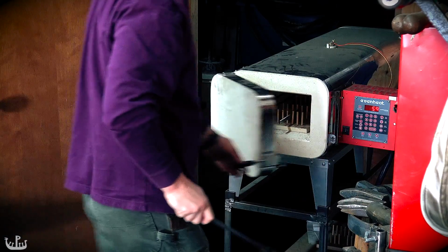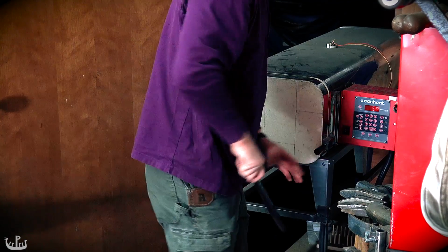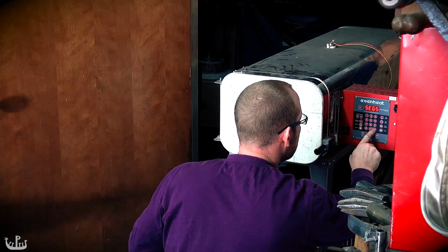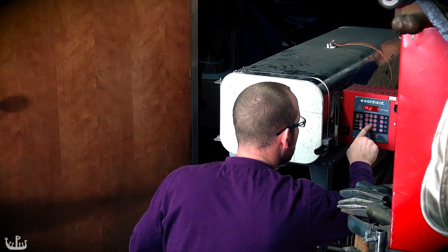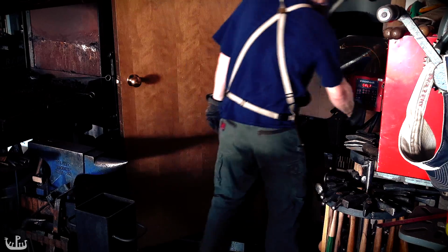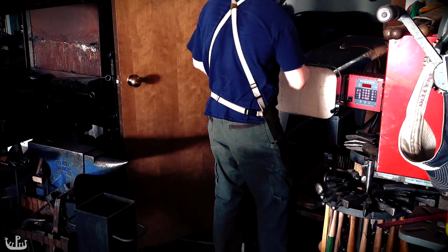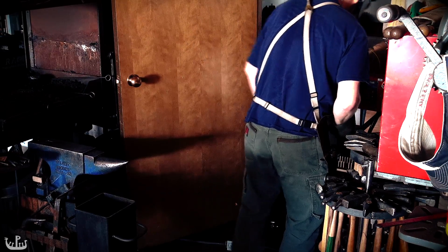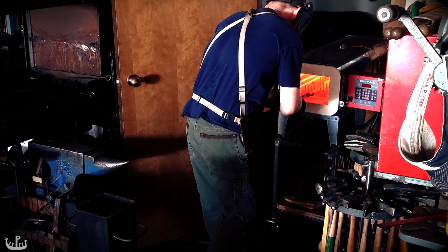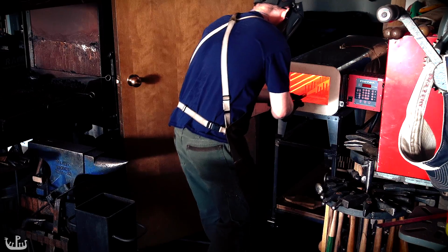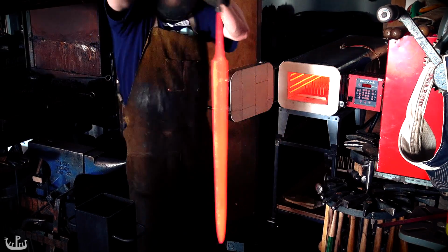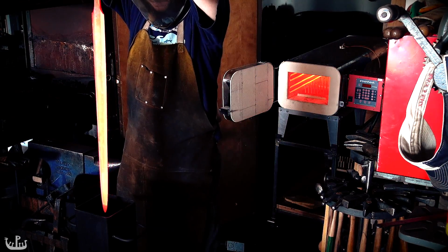I use a temperature-controlled kiln to bring the sword up to 1500 degrees Fahrenheit. At this temperature, the carbon is dissolved in the steel matrix. This is called austenite. By quenching it quickly, the carbon cannot move back into its normal configuration and the result is martensite, which is very hard. This is also the moment where the sword might break or twist horribly. It can be quite stressful.